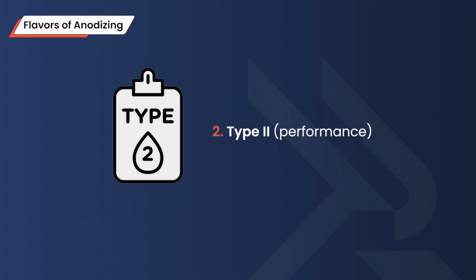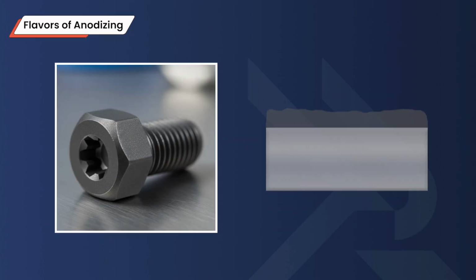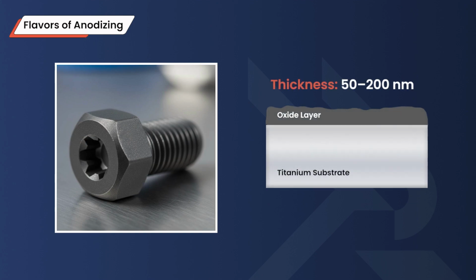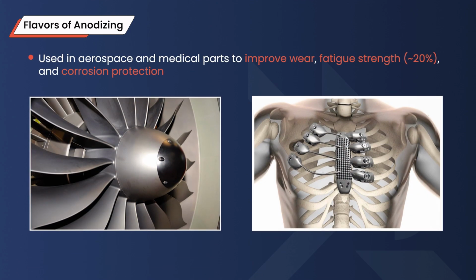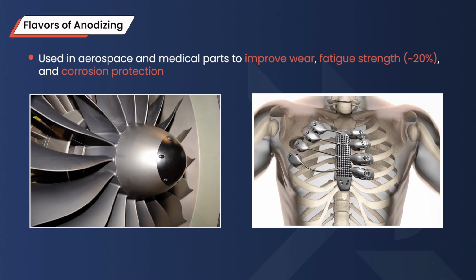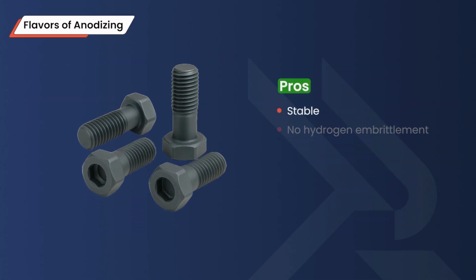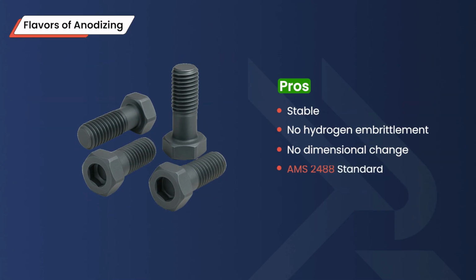2. Type 2, performance. This is a thicker, gray, wear-resistant anodize, typically around 50 to 200 nanometers. Aerospace and medical parts use it for improved wear, better fatigue strength, sometimes up to approximately 20%, and corrosion protection. It's stable, doesn't cause hydrogen embrittlement, and doesn't change dimensions, and many Type 2 processes reference AMS 2488 standards.